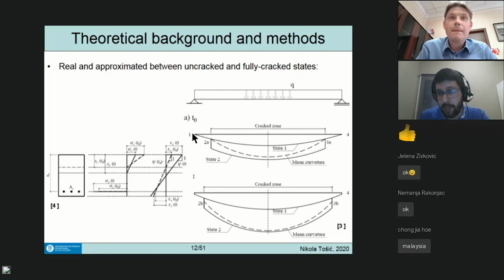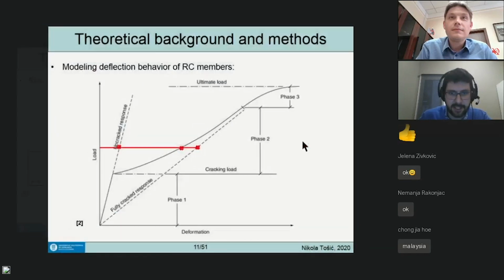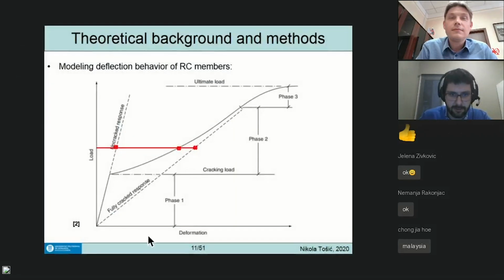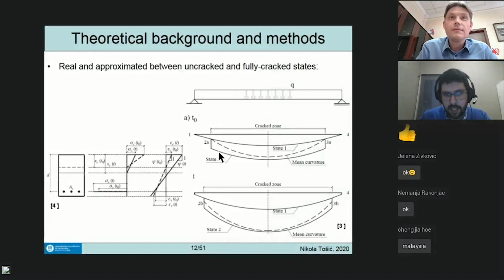The curvature of an uncracked section, which when double integrated gives the deflection, is this line here - a small curvature. But in the cracked zone, going back to the previous slide, the response of the fully cracked section has this larger curvature here. In reality, the mean curvature in the cracked zone is this dashed line.